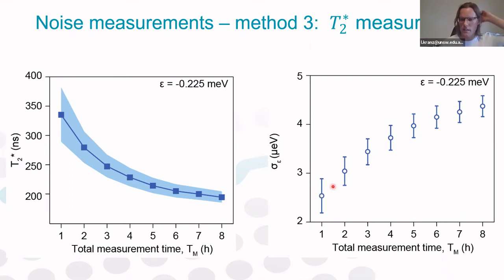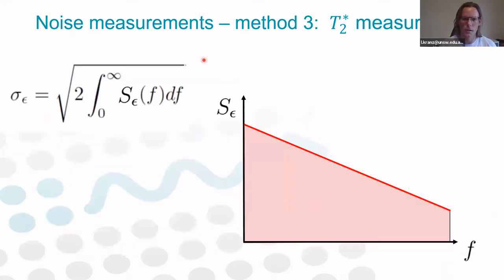Okay, so to understand and quantify this change of noise with total measurement time, we go back to theory. The theory tells us that regardless of what spectrum of noise you have in your device, your fluctuations in detuning are described by this equation, which is basically an integral over all frequency components. If I was to visualize it, if the red line is the power spectrum in a device, then sigma epsilon would correspond to the square root of this area here.